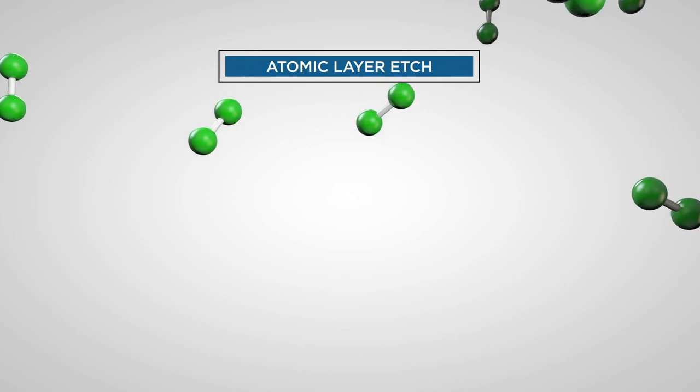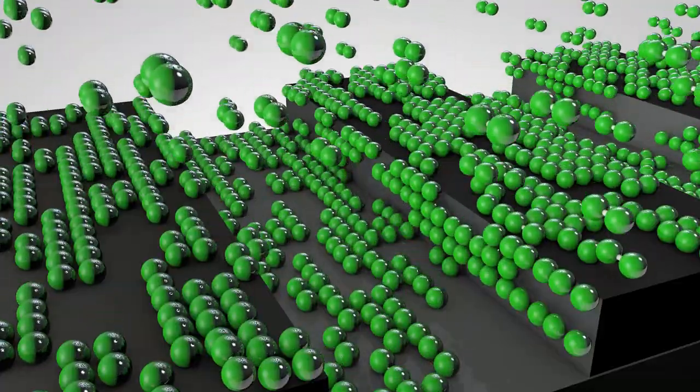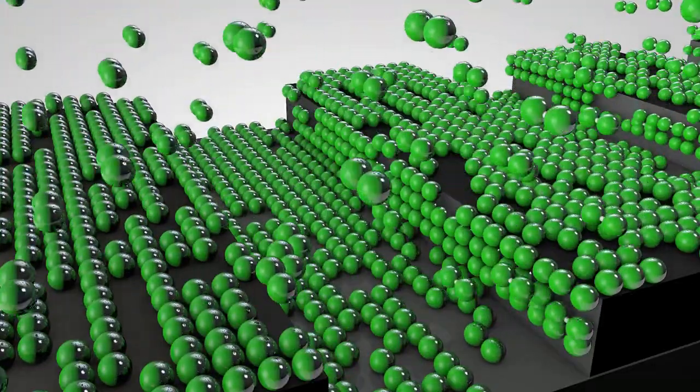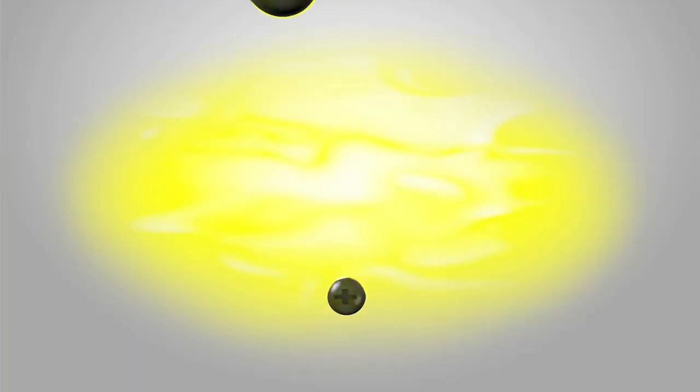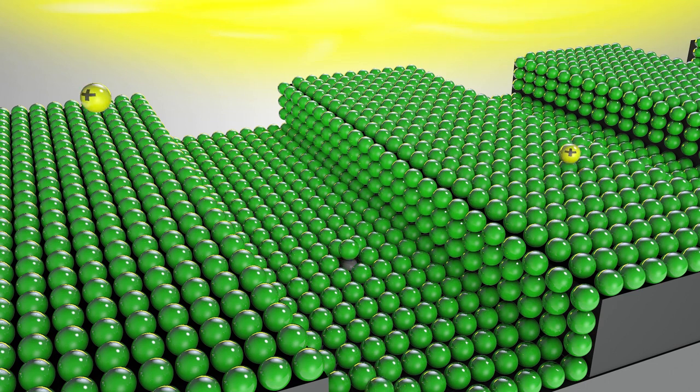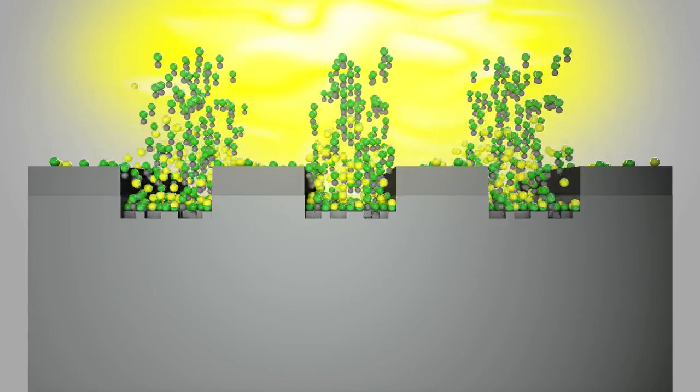But at LAM Research, we found a way to make it happen. The ALE process is based on the same concept as ALD in that the reaction steps are separated. ALE typically starts with an adsorption step to form a reactive layer, followed by a removal step, called desorption, to take off this layer.